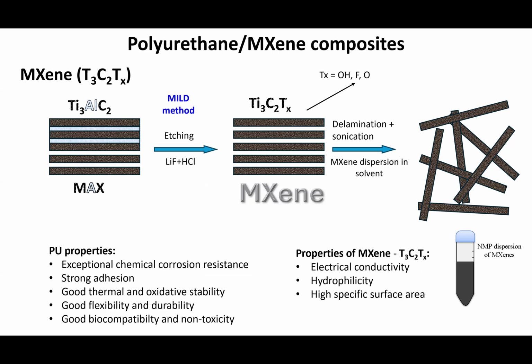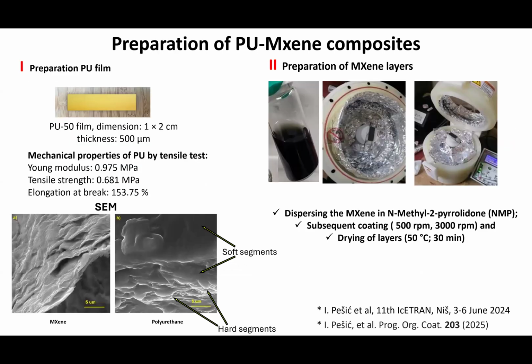The MXenes themselves have excellent electrical conductivity and a high specific surface area, so they're reactive. You can use them for different things. We deposit them on polyurethane substrates primarily. So we prepare our polyurethane film shown in the top left. The thickness of this particular film is 0.5 millimeter, or 500 microns, and then we perform spin coating to deposit MXene, but we perform spin coating several times to optimize the thickness of the MXene.